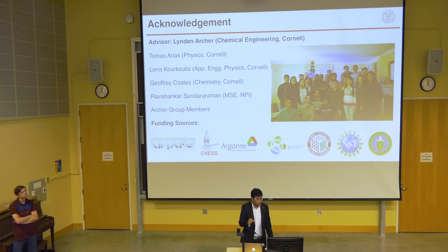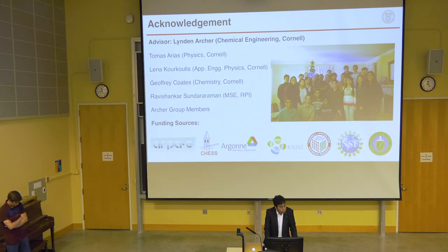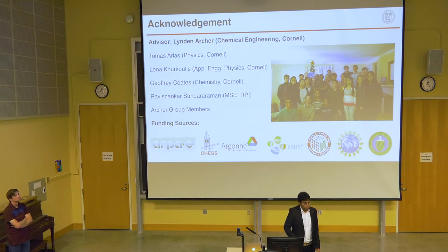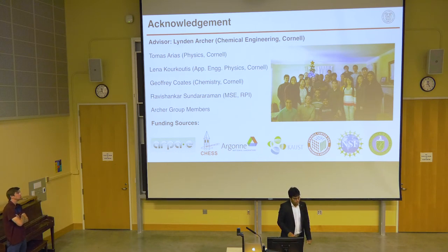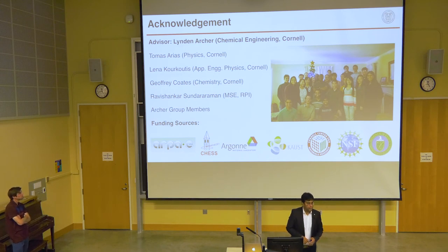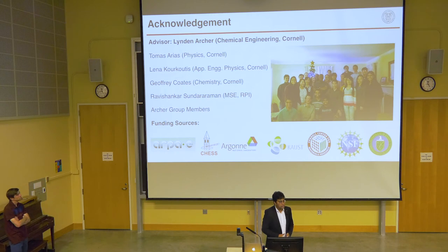To find out the thickness of the layer or how much is present. Yeah, I'm curious because if you have two lithium electrodes, you have infinite capacity, based on the thickness of those electrodes. So I just wonder, adding that layer is actually changing the chemistry of your battery completely, so that it's no longer lithium metal, but lithium metal in your layer, and it's just charging and discharging that layer rather than going through the metal itself. Yeah, so you can calculate the capacity of this interfacial layer, and it would come down to a very low value because it's a few nanometers compared to the full lithium metal.